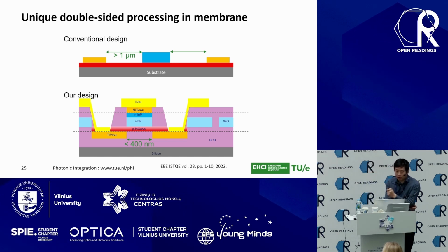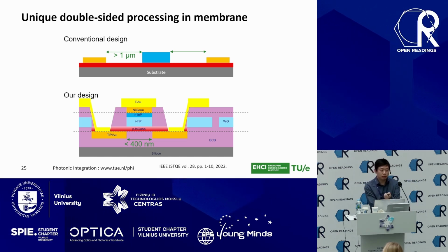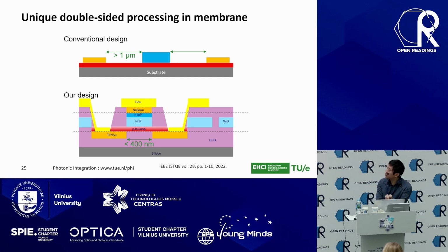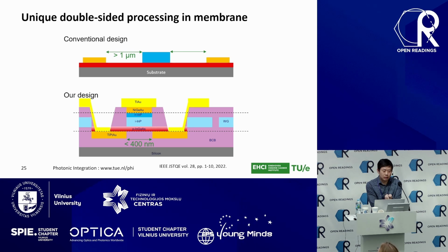If I compare our design to a conventional photodiode made on indium phosphide chips, the fundamental difference is that in the conventional design, everything is patterned and processed from the top side of your wafer, right? It means that your metal has to land on the top surface, and laterally, it has to be placed very far away from your waveguide. So in this case, if the blue rectangle is your detector waveguide, then your metal has to be placed on two sides, which has to be more than 1 micrometer.